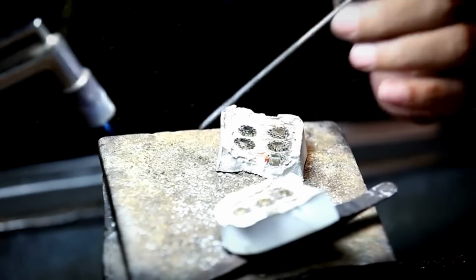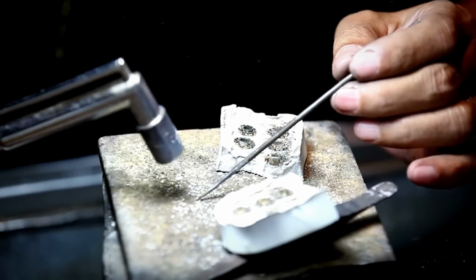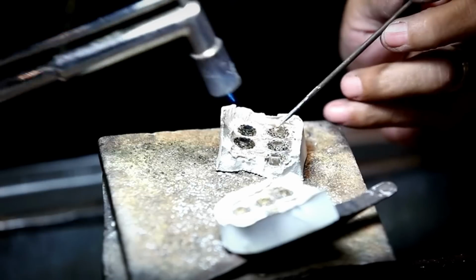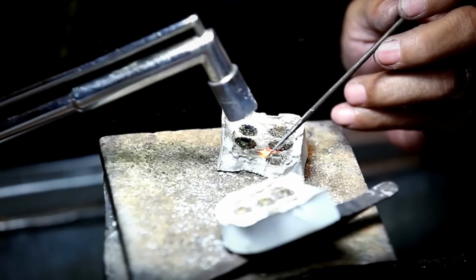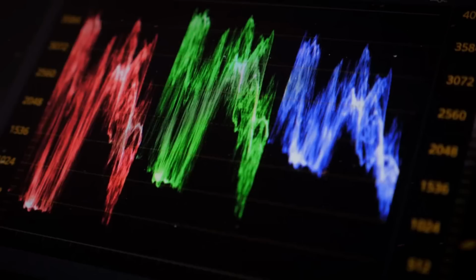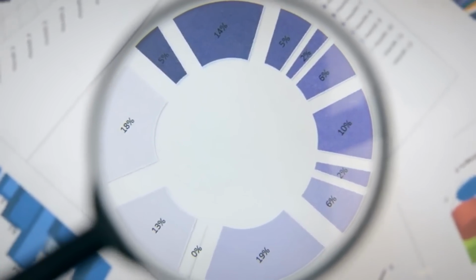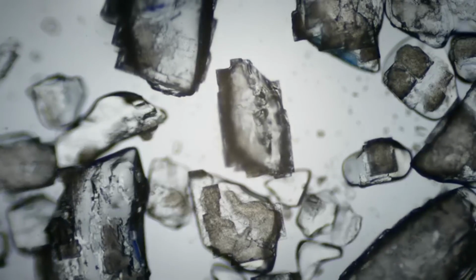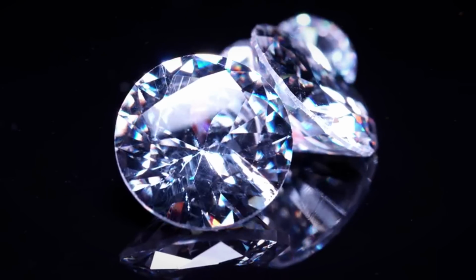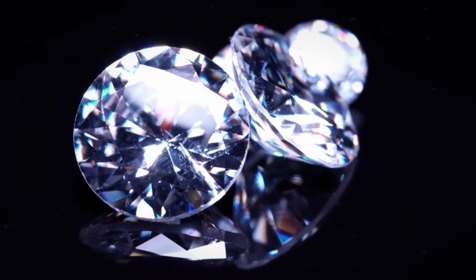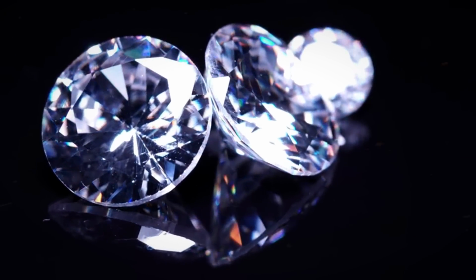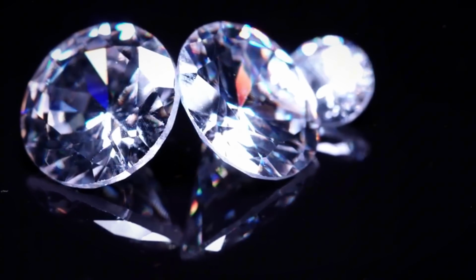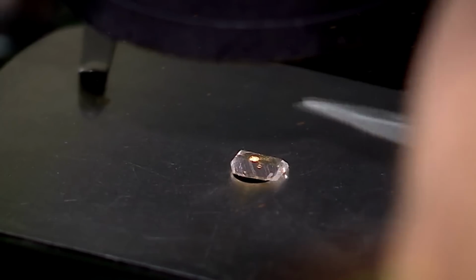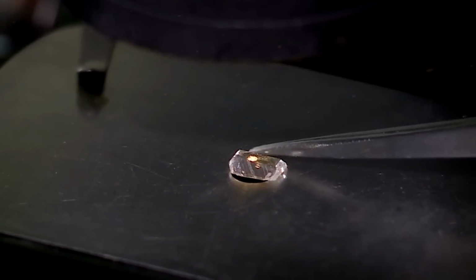When a stone reaches a recognized gemological lab, such as the GIA, Gemological Institute of America, SSEF, Swiss Gemological Institute, or NGTC, National Gemstone Testing Center in China, it undergoes a suite of standardized tests that go far beyond handheld tools. One of the most telling is infrared spectroscopy. This test categorizes a diamond by type based on nitrogen content and aggregation. Type Ia diamonds, containing aggregated nitrogen, are overwhelmingly natural. Type IIb diamonds, though rarer, can also be natural but are more susceptible to misidentification if lab-grown variants aren't ruled out.